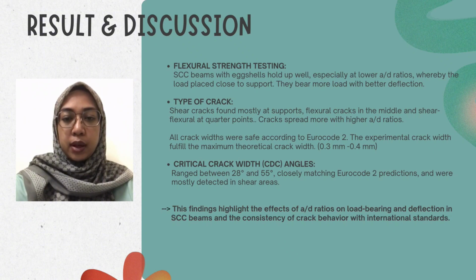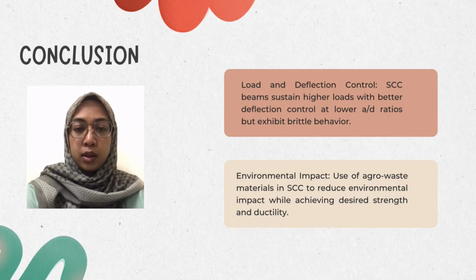So this finding highlights the effects of the A over D ratio on load bearing and deflection in SCC beams and the consistency of crack behavior with the international standards. In conclusion, SCC beams sustain higher loads and have better deflection control at lower A over D ratios, though they can be brittle. Using eggshell in SCC reduces environmental impact while ensuring strength and ductility for the structure.